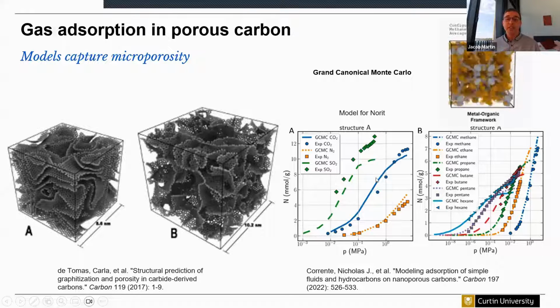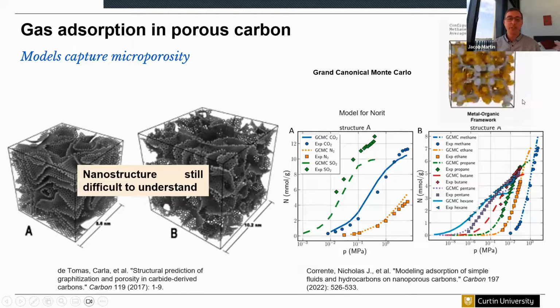And you can see here the simulated absorption curves for the quadrupolar gases, and also for these different hydrocarbons. And at least for the non-polar species, it seems that just the carbon network itself is enough to describe some fairly complex gas isotherms. And that was done using grand canonical Monte Carlo, which I can go into if you want more detail.